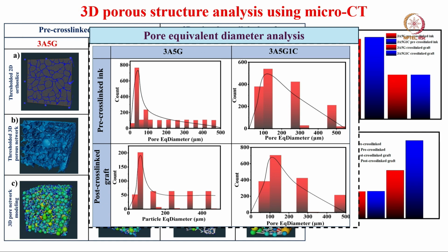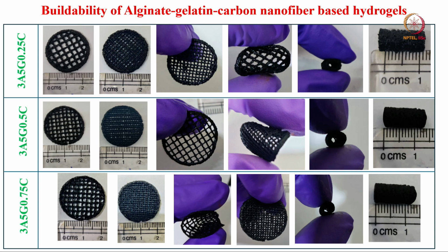Pore diameter analysis, this is all done using microcomputed tomography analysis, and you can see that the pore equivalent diameter measured is about 100 to 400 micrometers.